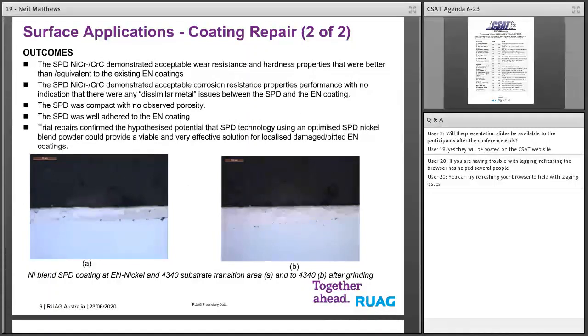So it's a nickel chrome carbide solution. It certainly meets the wear resistance requirement and the hardness requirements. It satisfies the corrosion resistance. We didn't see any issues with dissimilar metals.